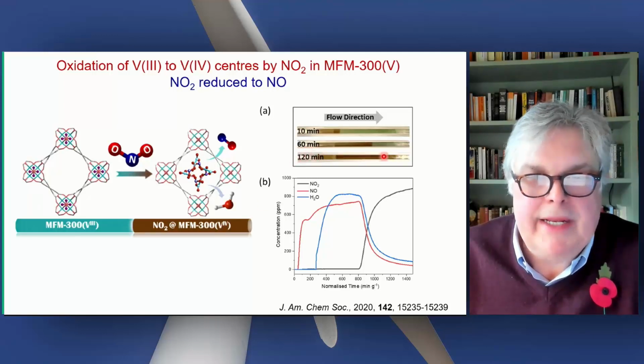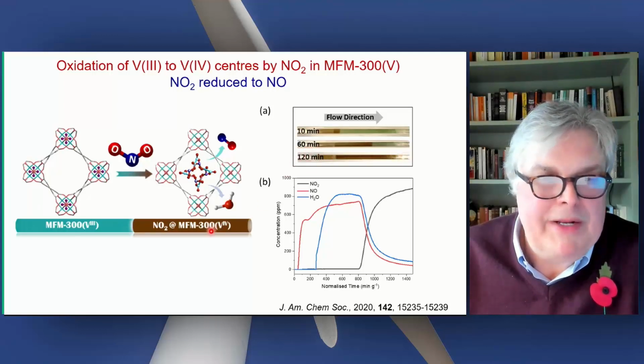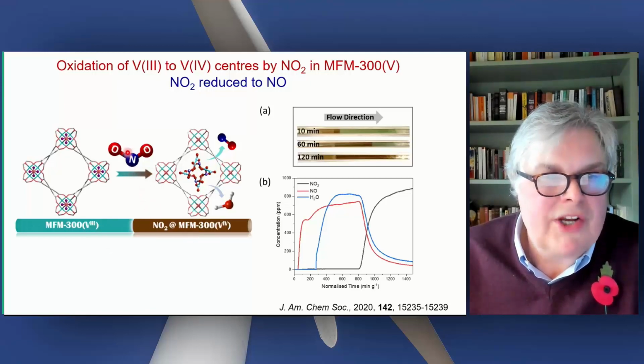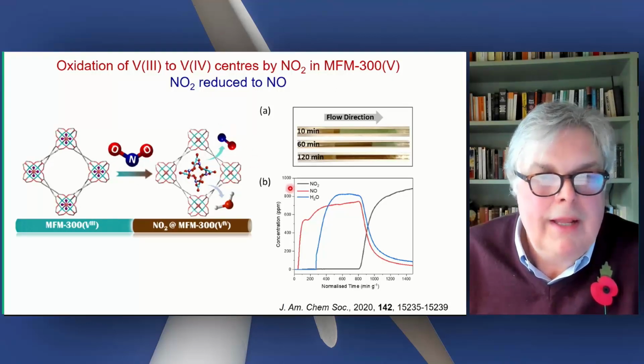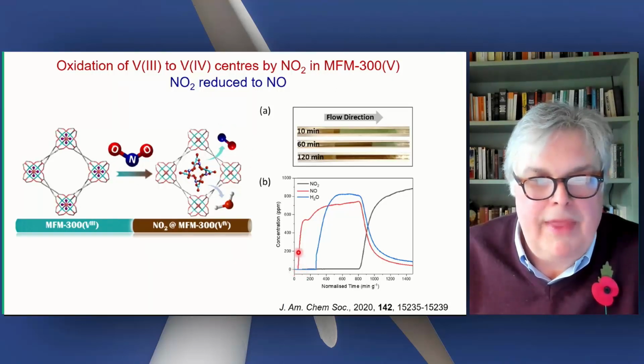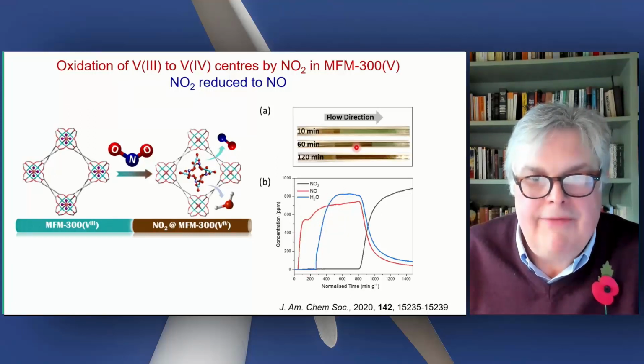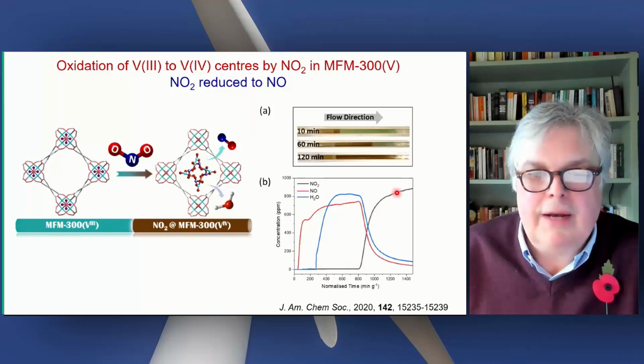After 120 minutes, the whole column has been oxidized from vanadium-3 to vanadium-4. And what's going on here is that the NO2 is being reduced to NO. And in the breakthrough experiment, there is the NO coming out. Here is water coming out. And eventually, as you get to this end, the NO2 comes out.